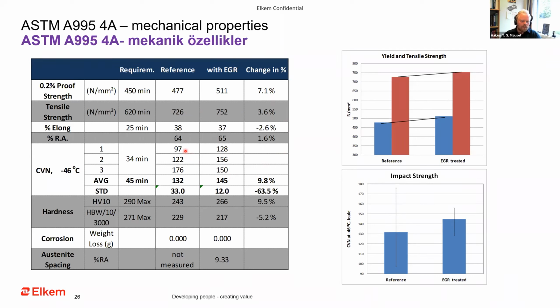You can see here that there is quite a lot of deviation between the 3 samples here. The average is about 132 joules. But if you look at the one with EGR, there is much less variation between the single values. And then we're at 145 joules. So an increase of 9.8%.